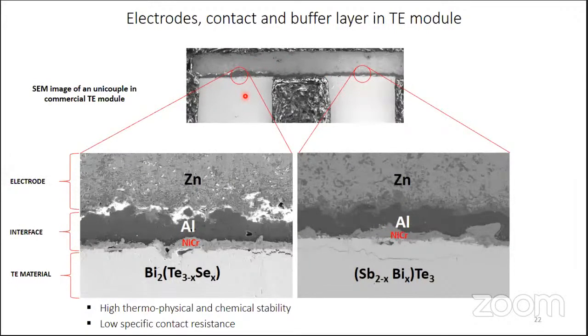Since the zinc melting point is low, it can diffuse into bismuth telluride. So they put aluminum as one barrier layer, the nickel chromium as another barrier layer, and then in between the zinc and this thing. So this is how they interface the hot side junction to prevent diffusion of zinc or aluminum into this. Because if zinc or aluminum are diffusing, then automatically the concentration of this thermoelectric leg will change. If the concentration changes, then the conductivity, Seebeck coefficient, everything will change, and in many cases the device will start degrading over the period of operation.